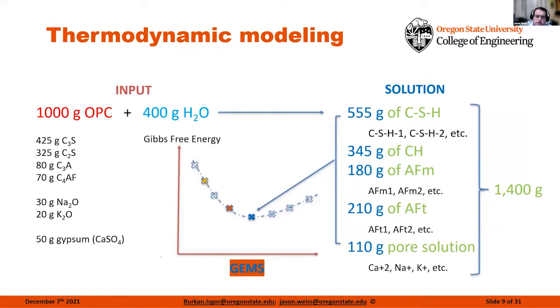Now, how we do this is by using this technique that I mentioned called thermodynamic modeling. This is really where Professor Isgor is really driving these models and doing a really phenomenal job, where we can start off by knowing our cement. We can break that down into constituent phases. We add water into that system, and we essentially go through a series of simulations to say, what happens if we predict these as the outputs?